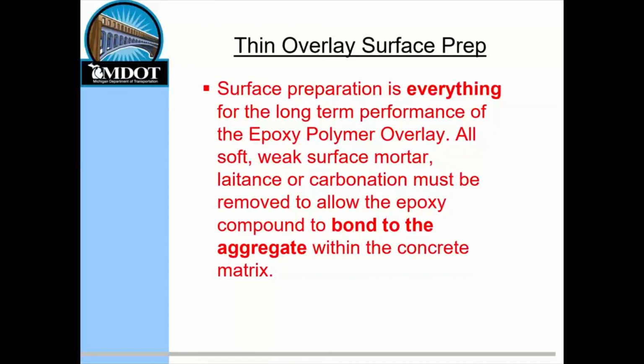Thin overlay surface prep. Surface preparation is everything for the long-term performance of an epoxy overlay. All soft, weak surface mortar, laitance, carbonation must be removed to allow the epoxy to bond to the aggregate within the concrete matrix. We pulled this out of a couple of sources, and you'll notice that it doesn't say allow the epoxy compound to bond to the cement paste or anything else. It says bond to the aggregate within the concrete matrix.